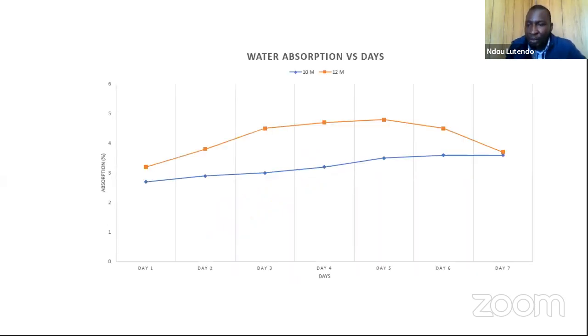Now, I actually put it under water absorption just to actually see what happens if you build with geopolymers. What would happen if it rains for like 10 days? Wouldn't that building just melt because it has more water? And what we actually found out in this study is that day 1, I actually found a very low water absorption percentage, which was about 3%. And when we go to day 4, it increased. And that was a concern for me at about day 4 and day 5. It was a concern that it seems like this experiment is going to fail. Because if it's increasing, it means it may constantly increase.